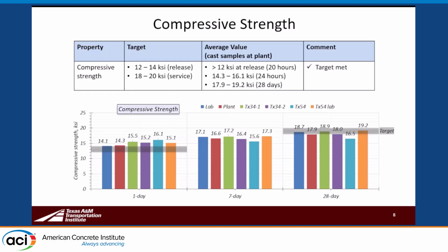And so for 1 day, we're doing fine in terms of getting that required early release strength. Because of that high early strength, it's interesting that we're not seeing as much increase over time, but we are hitting the high early and by and large hitting the target strength at 28 days.